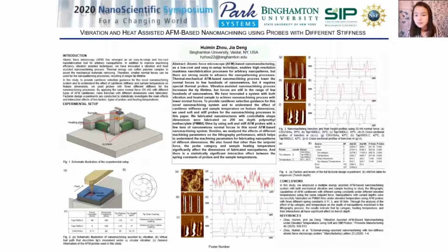The types of tips we used are in Figure 2C. The first one is TAP 190 DLC. It's a very stiff tip with spring constant 48 Newton per meter. The second one is TAP 150 DLC. This tip also has diamond-like carbon coating. It's wear resistant with spring constant 5 Newton per meter.